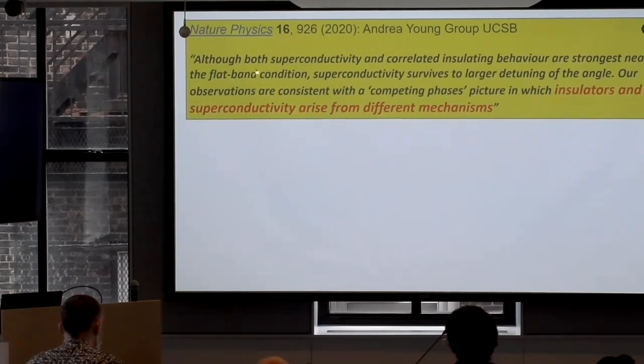So I'm just quoting from the abstract. Although both superconductivity and correlated insulating behaviors are strongest near the flat band condition, superconductivity survives to larger detuning of the angle. Our observations are consistent with a competing phase picture in which insulators and superconductivity arise from different mechanisms. And this is what I was saying, and this is what Andy was saying, what happens in cuprates, that superconductivity is preempted by correlated insulator. If you go to large angles, superconductivity survives and becomes much bigger.